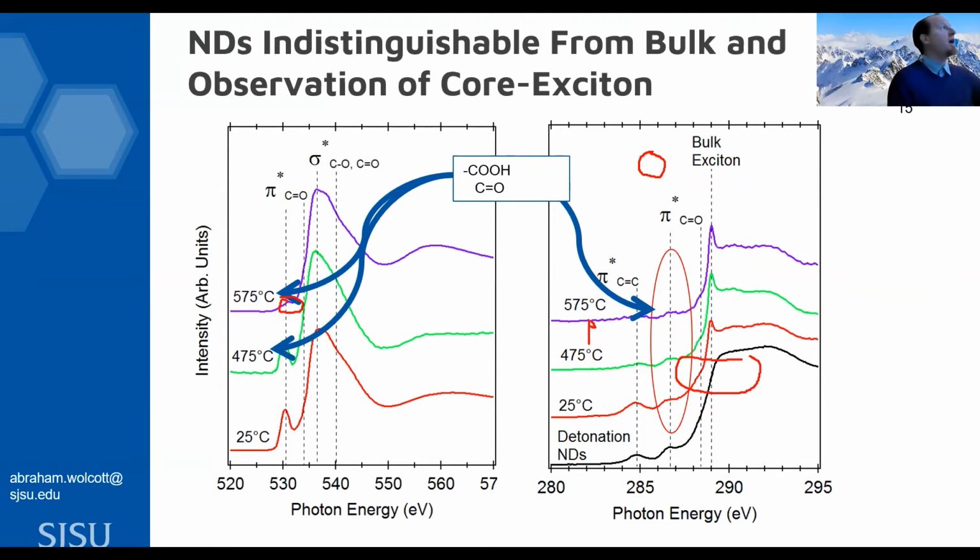Those unstable carboxylic acids were being purged from the diamond surface, leaving the most stable moieties. We would argue that the most stable moieties available to us would be those alcohols, the alcohol groups supported along the 111 crystallographic facet, because it can only support a single sigma bond. So this is the kind of mind frame that we wanted to use to manipulate the surface.